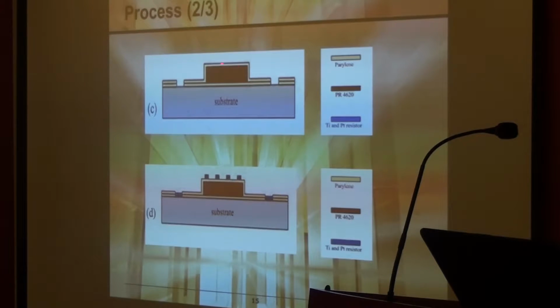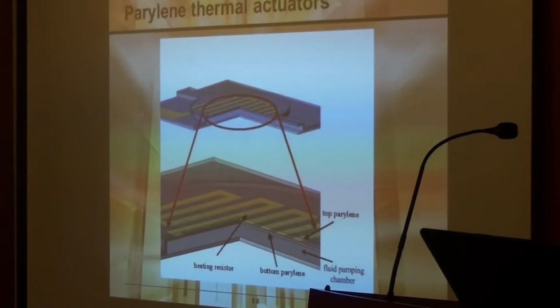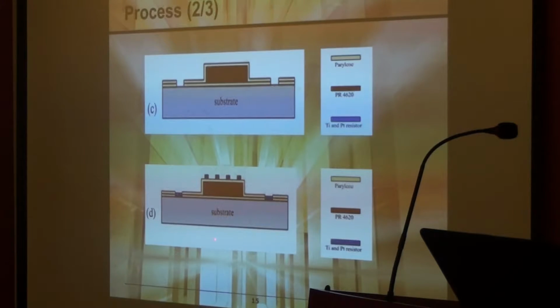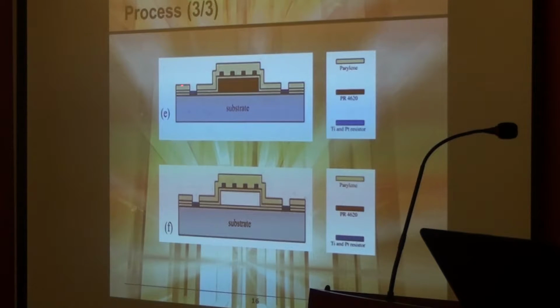Okay, after completing the chamber structure, the next step is the heater. So here we put in some heating metal, the resistor, with the in and out as two electrodes. Not only that, we keep going with the top layer, the third layer of parylene. So we coat the polymer several times, exactly coating the heater.